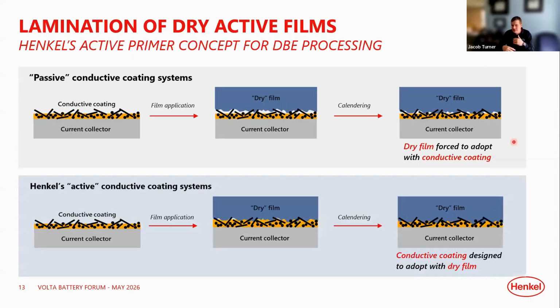So what Henkel has done is develop what we'll call this active coating system, where this coating now starts to behave truly like an adhesive. So what happens here is when we do this film application, this dry film, our material is actually going to adapt with that dry film. This allows almost a wetting of the surface of that dry film to really increase that bond strength at that interface and therefore enhance our conductivity.